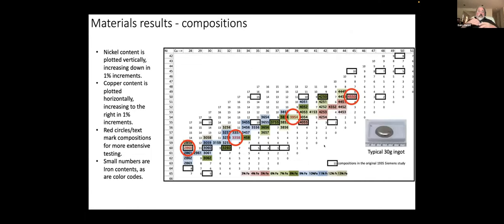Into some of the data. So here I show all the different alloys we made. For each alloy, we made a 30-gram ingot. These were melted in Iowa by David, and then sent here to Vancouver for me to roll them and process them into testable materials for magnetic properties. David took several of these materials, the ones that I've outlined in red circles, and actually built magnetometer sensors out of them so we could compare performances of these with each other and with the legacy materials.